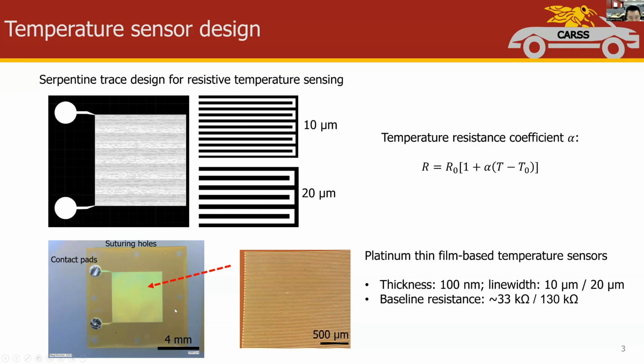We expect the baseline resistance to be about 33 kiloohms and 133 kiloohms, 130 kiloohms respectively. Such large resistance is able to overcome the effect from the lead resistance. The platinum layer was positioned between two layers of polyimide, and we also left several holes at the boundary of the sensor for suturing purposes.